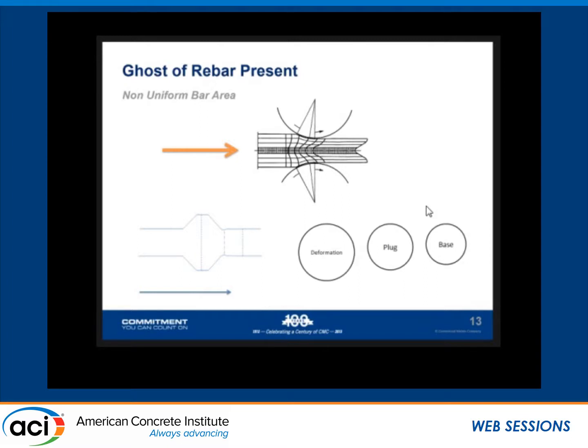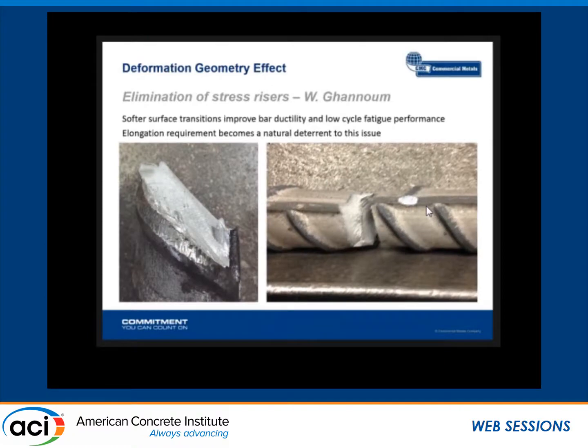But if you look, you've got an area for the deformation, you've got an area for the plug, and you've got an area at the very base of the deformation that's smaller than all of them. So ultimately, your smallest area determines your strength. Right here, this is the thing that fundamentally determines how strong the bar is: the bottom of the deformation where we have the stress riser and everything else. I know in some of the research that we've seen, the bottom of the deformation has become almost a critical point of failure.